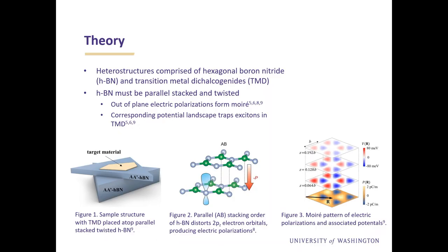We constructed our samples by stacking a monolayer semiconductor, in this case a transition metal dichalcogenide, on top of two layers of insulating HBN that have been twisted relative to each other. This sample structure is interesting because if you parallel stack the HBN layers, meaning they are oriented the same way,